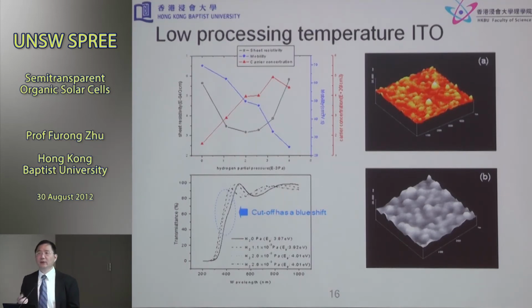You know that in semiconductor materials, the doping controls the conductivity of the material, while in ITO, the dopant is controlled by the indium, tin, and also the oxygen vacancies. So during the fabrication of ITO, if you're able to control the oxygen vacancies, and an oxygen vacancy theoretically contributes two free electrons, then you can tune the conductivity. Of course, there has to be an optimum range.